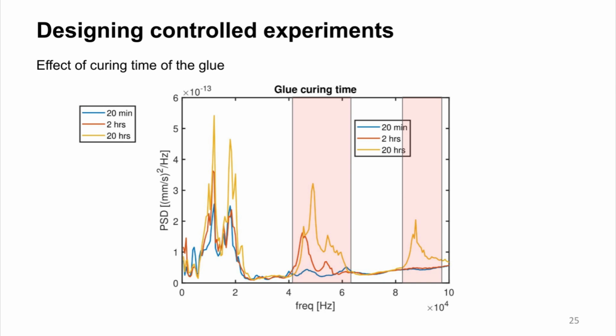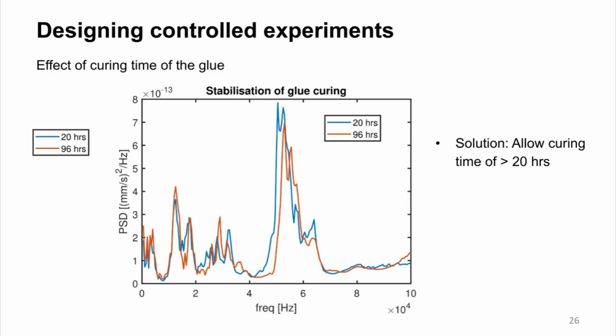But then I also found that for a curing time of more than 20 hours, for example, here I compare 20 hours and 96 hours, there isn't an appreciable difference in the power spectral density curves I get for the metamaterials. As we can see, for any time more than 20 hours, the curing time does not have an effect on the power spectral density. And these measurements were done within a single gluing session. The piezo was not unglued and reglued, adding an additional factor to the experiment.